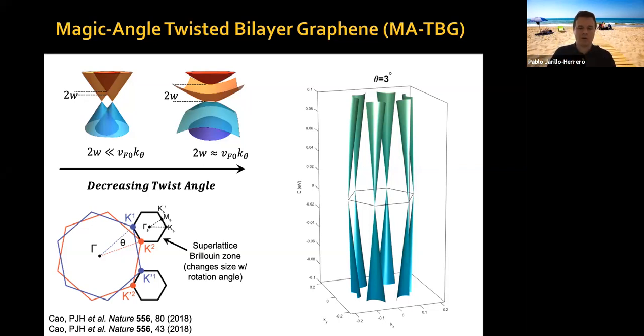It's a small reciprocal space, and now this is the electronic structure for a relatively large angle, 3 degrees. Within this energy window, you can see this just looks like graphene: Dirac cones coming out of the superlattice Brillouin zone K points, okay? Now, as I run this video, the first thing that you're going to see is that the angle is going to go towards smaller angles, which means this superlattice Brillouin zone is going to become even smaller and smaller, okay? And it's going to rotate. And then you're going to see what happens with the energy bands.